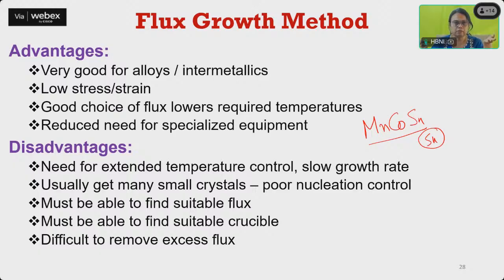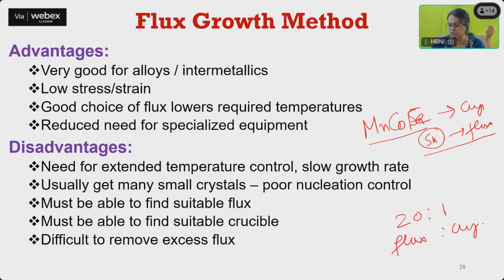The melting point of tin is very low, or Fe you can have. So all are very high melting point materials, but they can all dissolve. But here the ratio of the crystal you are growing and the flux is very important. So flux is taken in a very large amount, like 20:1. This is the flux by weight, and this is the crystal you are trying to grow. So this is by weight.